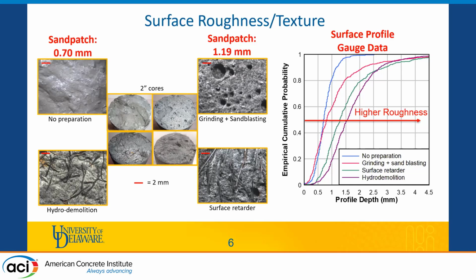These 2 methods are comparable in terms of exposing the fibers, and that also hindered using the method of sand patching. You may notice that I haven't mentioned any results from the ICRI chips, and that's because UHPC is different than normal concrete in its nature. What I mean by that is that UHPC doesn't have aggregates, and some of these methods either expose the fibers or open up some bubbles, which is different than normal concrete that the ICRI chips are made for.